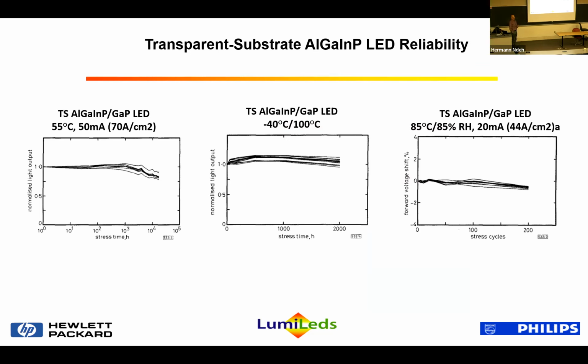The wafer bond was very mechanically robust, so it passed all reliability tests. So this is 17,000 hours of accelerated aging, which projects out to over 100,000 hours of operation, as well as liquid-liquid thermal shock, temp cycle, and wet-hot humidity testing as well. So, a very mechanically robust interface.